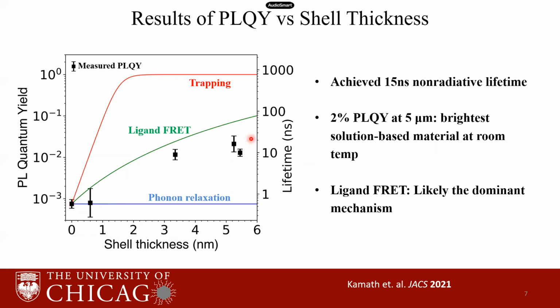By comparing the experimental trend with the three models, we can see that the experimental trend matches fairly well with the ligand FRET model. Though the agreement is not great and there is deviation for the larger thickness, this disagreement is likely due to the growth of the shell not being perfectly spherical, and there being defects at the core shell interface, which reduce the quantum yield. But overall, this result shows that ligand FRET is likely the dominant non-radiative mechanism.